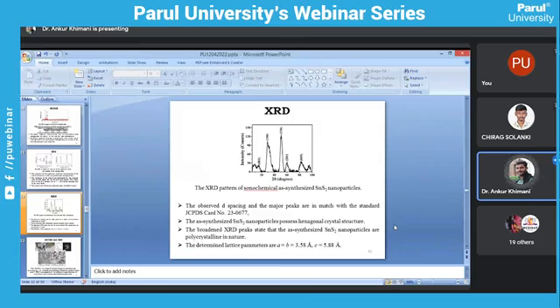XRD: the structure of the grown nanoparticle has been confirmed by XRD, X-ray diffraction. Over here is the intensity versus 2 theta graph. We get the 001, 100, 101, 102, 011 and 005 peaks. All the peaks are matching with the hexagonal phase of SnS2. The observed d-spacing and major peaks match the standard JCPDS card number 23-0677.